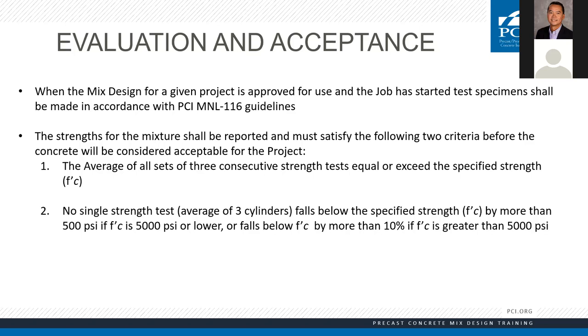The average of all sets of three consecutive strength tests needs to equal or exceed the specified strength — this is a moving three average. So if we have a 7,000 PSI specified strength, and yesterday's test was 7,500, today's was 7,800, and tomorrow's is 6,900 — one individual test is under strength, but the average of those three still exceeds the design strength. According to ACI and PCI, that's still an acceptable mix design. There can be low strength points and still be an acceptable mix design.